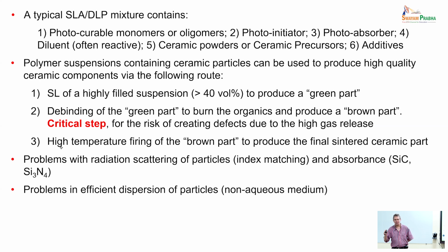Actually, now you can do it using some tricks. Either you use a high-intensity source, and I mean a polymeric DLP printer would have a light source that is maybe 5 milliwatts per square centimeter. And for processing silicon carbide, you need to go 50, 60, 70 milliwatts per square centimeter. So you need expensive hardware. Or what people have done, since the problem is the absorbance, is they oxidize the silicon carbide powder, and this creates a silica layer that does not absorb, has a low refractive index with respect to silicon carbide, and in this way you can consolidate the system. But then you have oxygen that you need to remove at very high temperature.